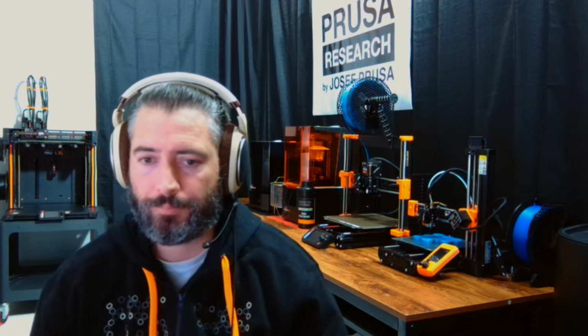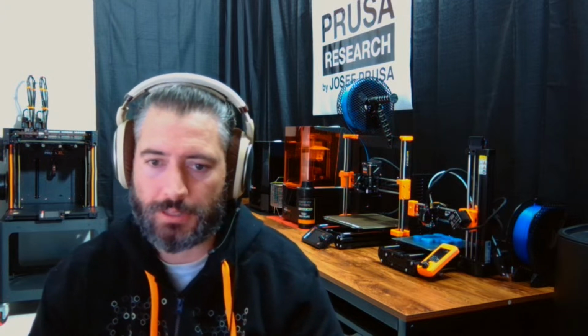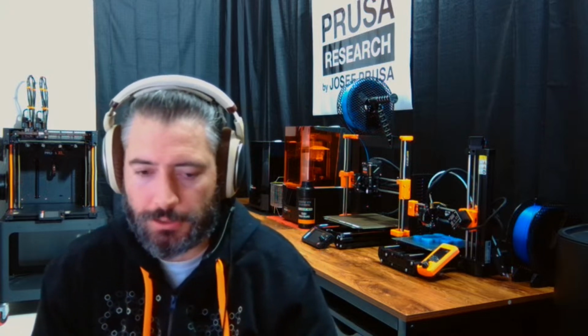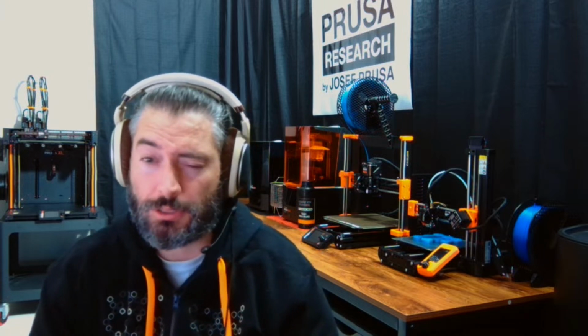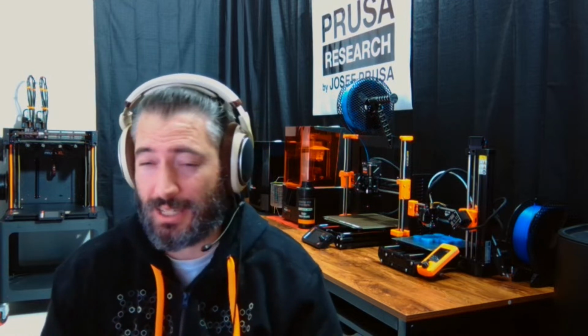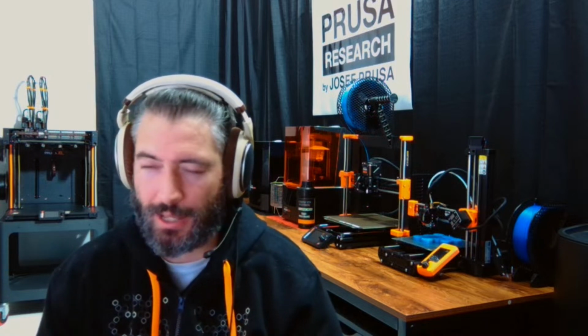Yeah, he says he needs to see through it. Unfortunately, you probably want to do resin for that. And I know with yellowing that becomes a problem, ambering for some of the resins. So if that's the problem you're running into, there are two things you can try. They have UV inks. You can take a UV ink that's purple and mix just a hair of purple into the mixture, so it has almost a purple hue to it.